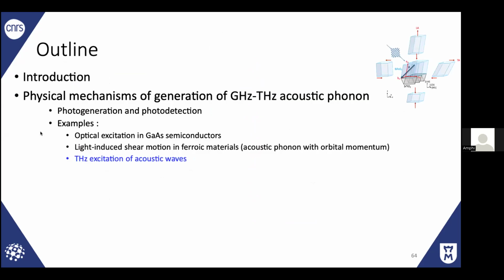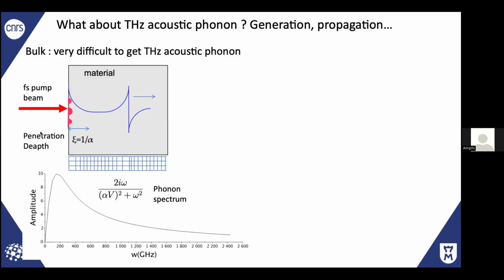So just to finish, I would like to tell you a few words about THz excitation. I told you this is a spectrum that you know now. For a semi-infinite system, you are always limited. It's very difficult to reach THz, because it's nearly impossible to deposit energy only on the surface. Or you can get it if you have, let's say, a graphene layer. It starts to work. You have very small layers, like a Dirac, and in that case, you can shift that frequency to the upper frequency.